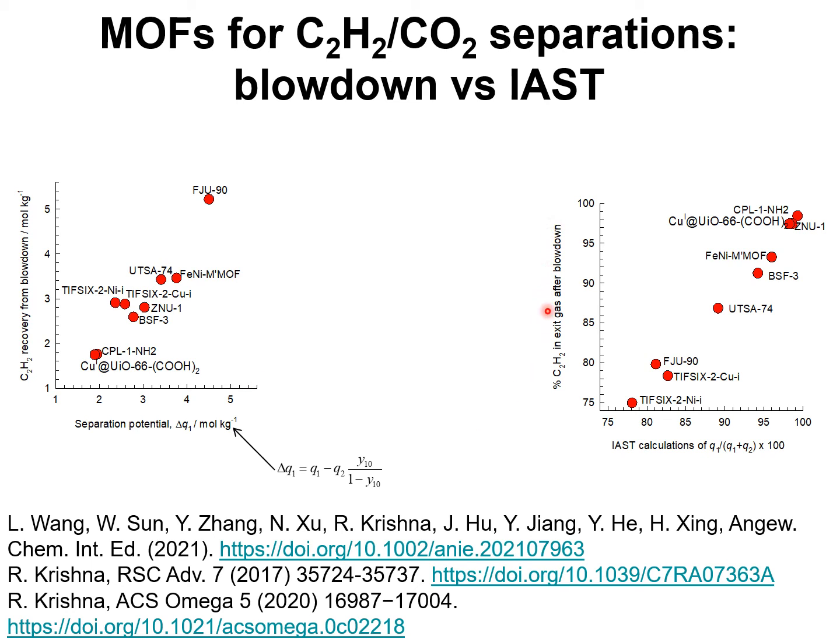Let's examine the product purities that are realized after vacuum blowdown. These are the values from the vacuum blowdown simulations shown in the previous slide. They vary from 75% purity for TIFSIX-2-Ni-I to about 97% for these three MOFs.